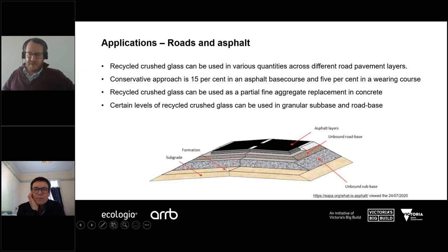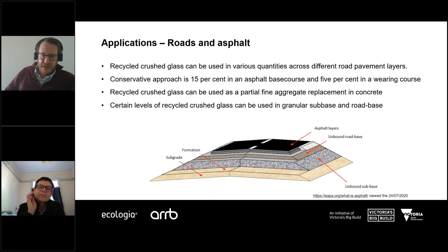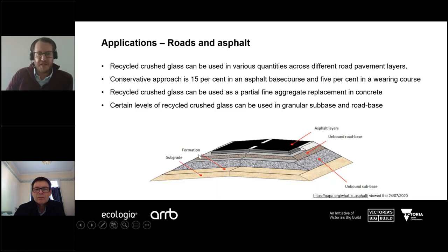Typically on top of our subgrade, we would have an unbound granular subbase material, potentially an unbound road base, a higher quality crushed rock. And then at the top, we would have our bound or sealed layers, which could be a sprayed seal to protect the unbound granular road base, or we could be considering asphalt layers or even concrete layers. And that gives us a number of opportunities to use recycled crushed glass. Typically we would be using recycled crushed glass as a fine aggregate replacement. Typically our recycled crushed glass is a passing 5mm, or passing 4.75mm product, so a graded product that would be fairly similar to the natural sand portion in our road infrastructure.